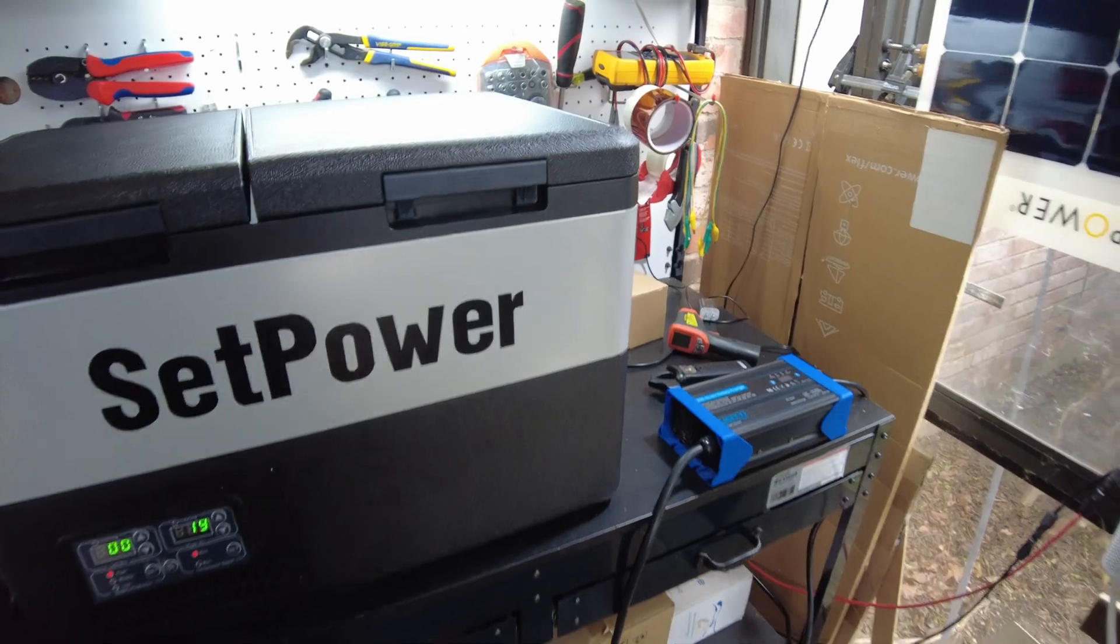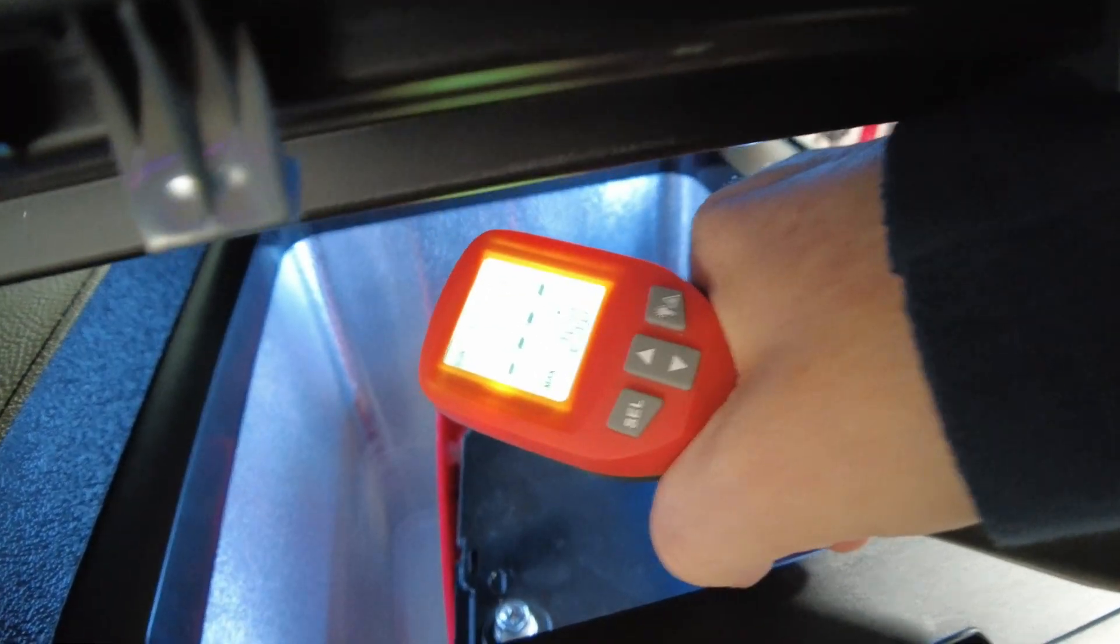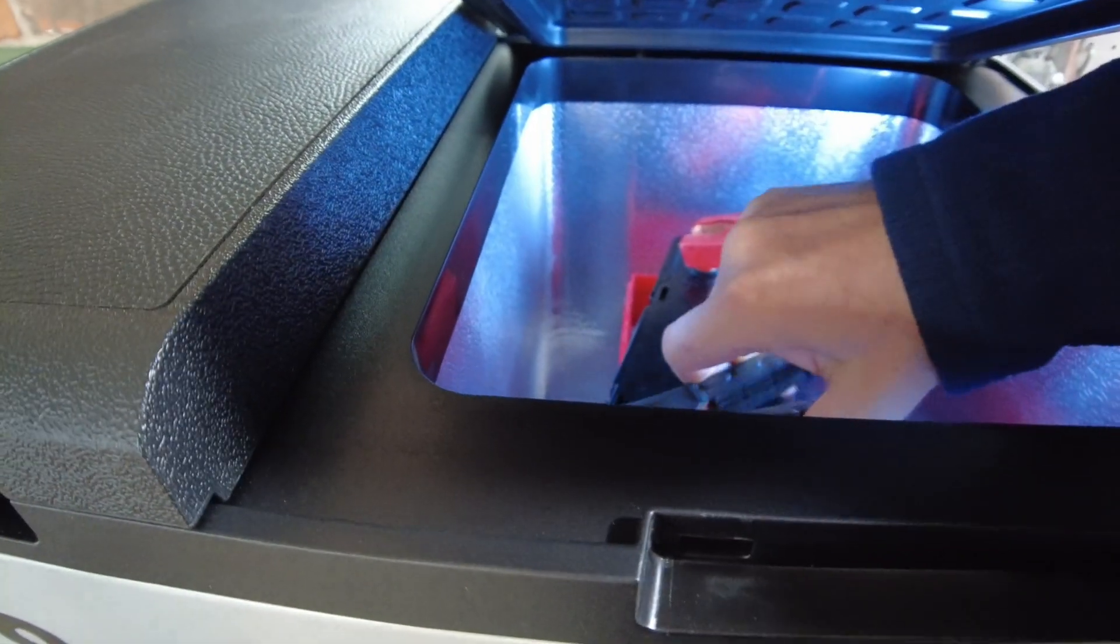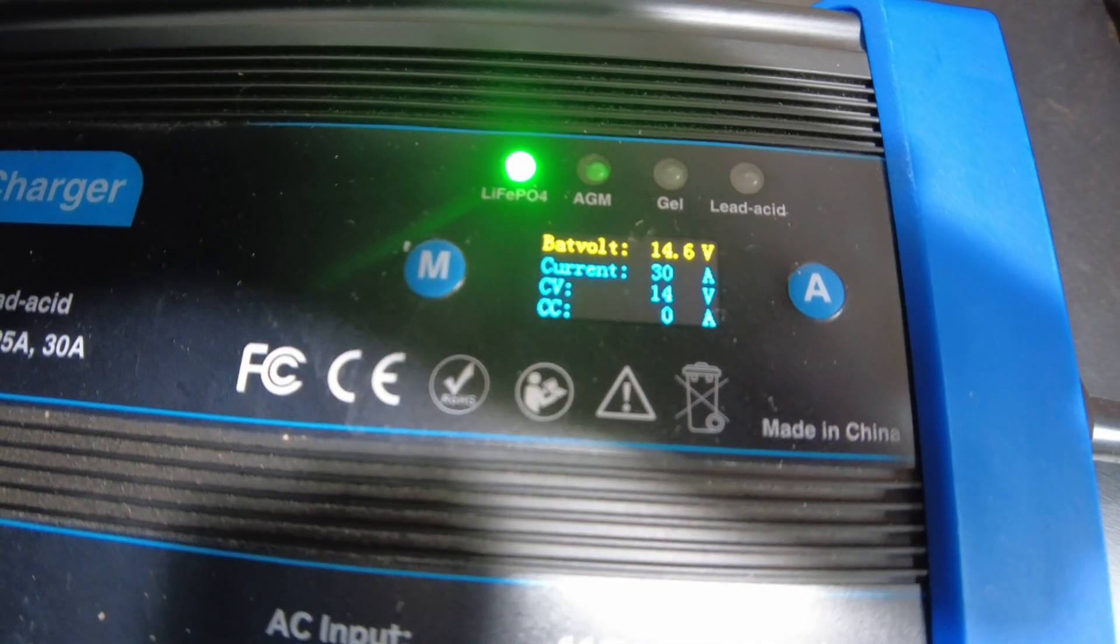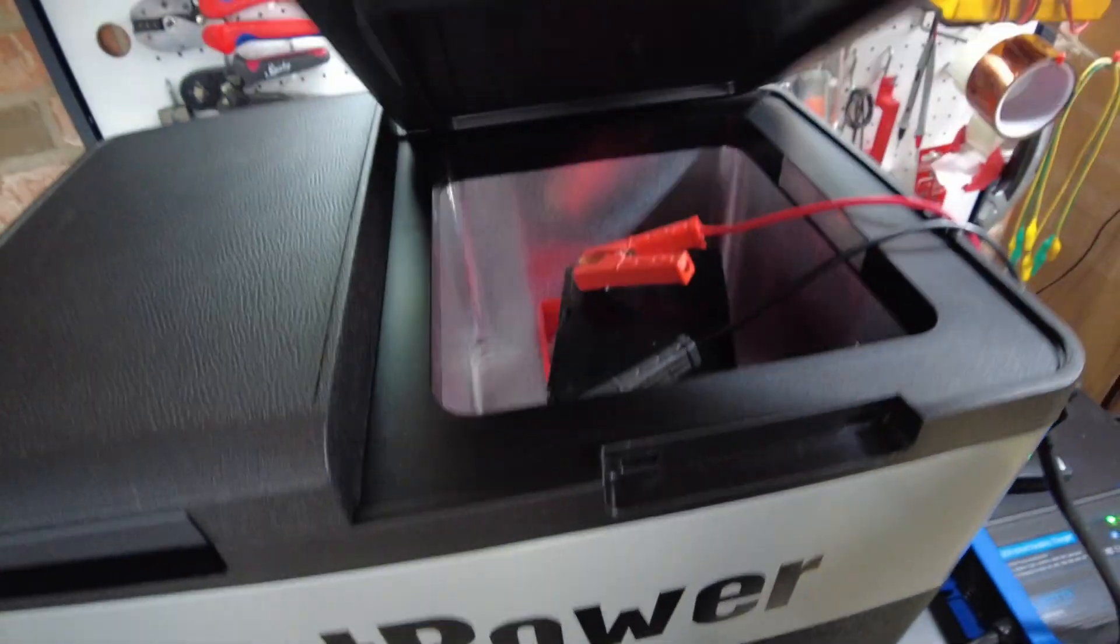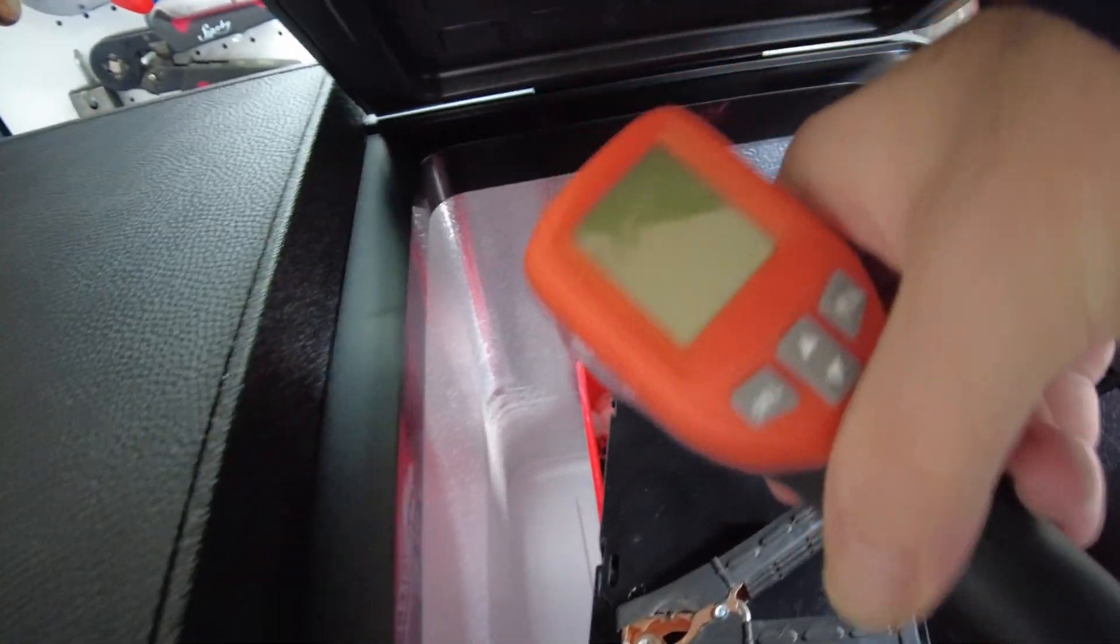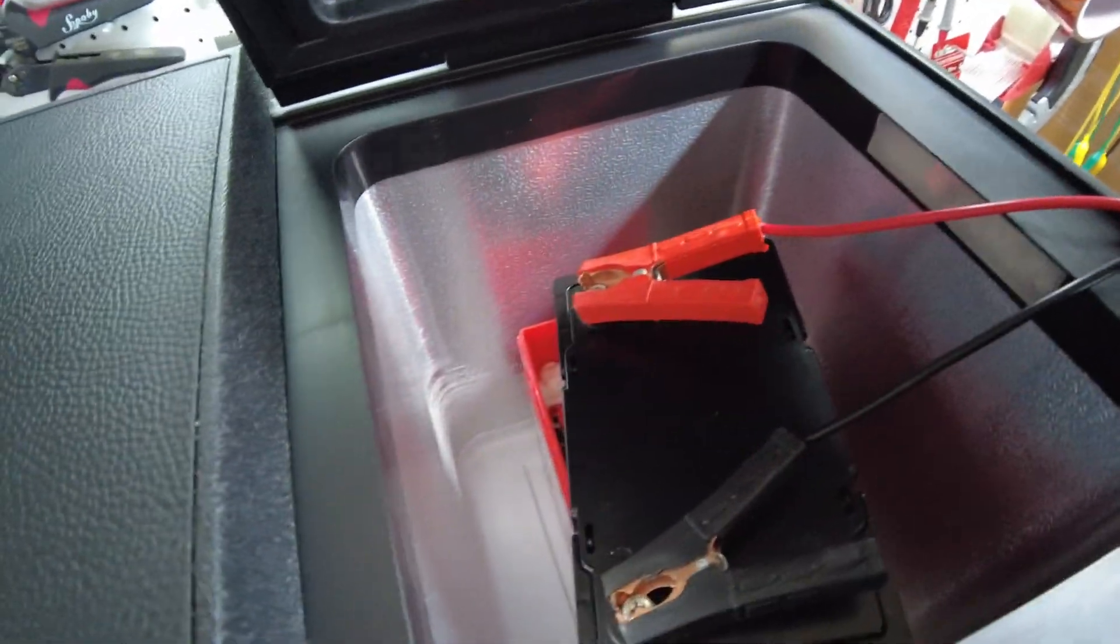Alright, it's been quite some time here. It's saying 19 right here. I think it's a little warmer than that inside. But let's go ahead and check. Yeah, it's right at 25. So let's hook it up. I don't think it's going to charge. No, it's not going to charge. Yeah, that's good. I think that's good enough for me, guys. It seems like the low temperature protection certainly does work. I think I'm actually going to let this battery thaw out now.